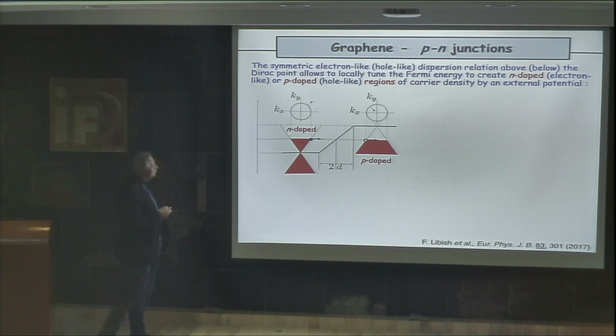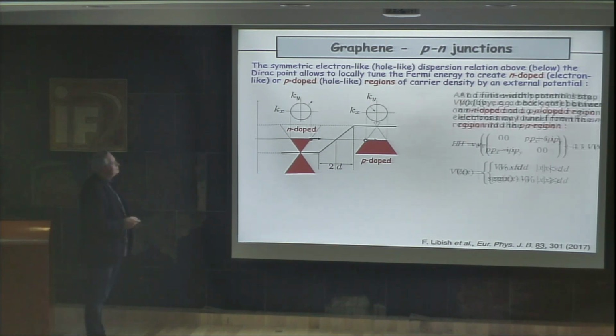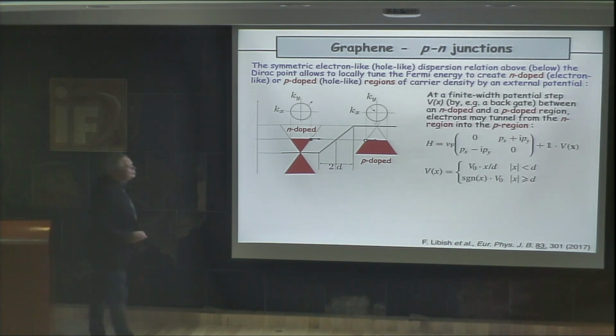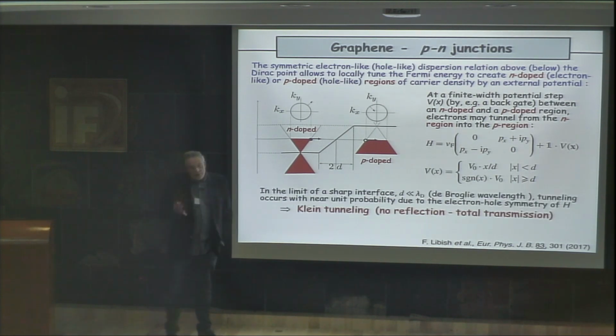And in fact, electrons can go through this barrier. This is very easy to model. You have to add just this term in the Hamiltonian, which takes into account a certain slope for the transition. Okay, let's suppose now that the slope is extremely abrupt. This means that d tends to 0 in this case, and well, it's not exactly 0, but it should be at least below the de Broglie wavelength.